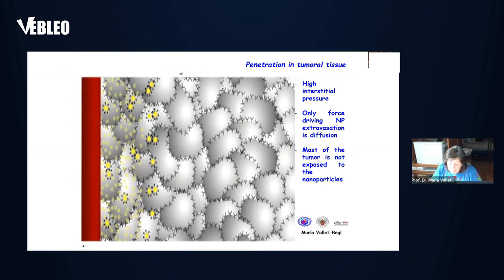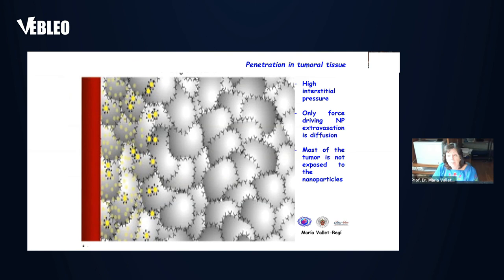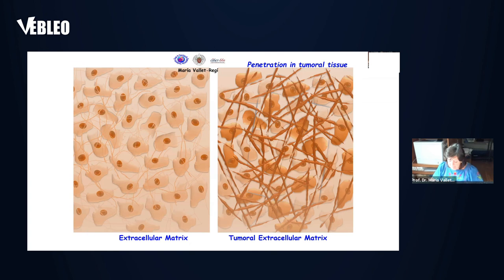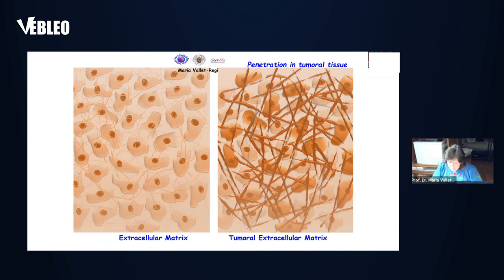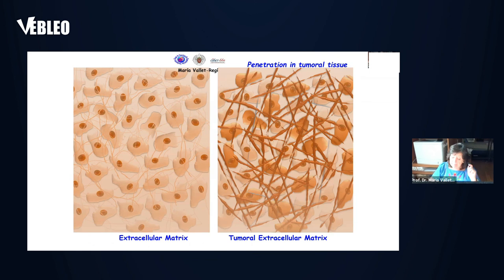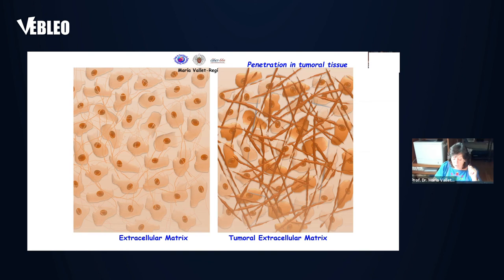Another very important aspect in nanomedicine is the low penetration of nanoparticles inside the cells. This has to be solved if we want this system to work. The tumor extracellular matrix is characterized by its high collagen content. This dense extracellular matrix hinders the nanoparticles and limits the effect of the drug carrier to the tumor environment. One solution is the manufacture of collagenase capsules attached to the nanoparticles. In this way, we have observed that the internalization reaches almost 100%. These capsules can be very useful in other applications, as you will see in the following video.